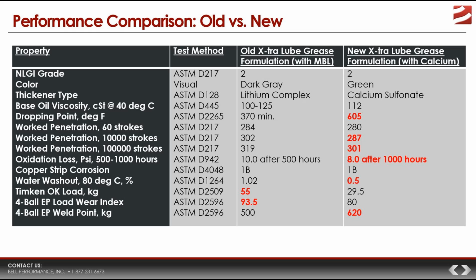The old X-tra Lube grease still stays within those parameters, so it's still graded as a good grease. But the new grease, at 100,000 strokes, is only at 301, a change of 21 grade units instead of 35. So there is significantly better performance in the work penetration test with the new X-tra Lube grease. That's advantage number 2 - better shear stability. Advantage number 1 was better dropping point.